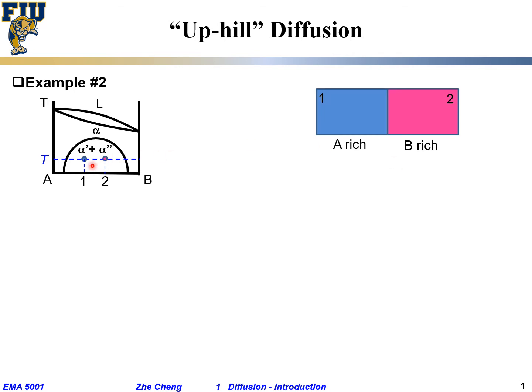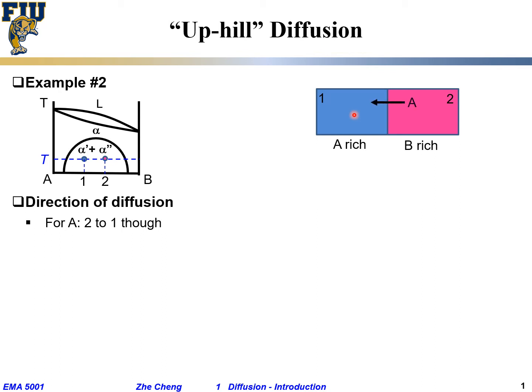When we put them together, based on the equilibrium phase diagram, will this eventually form a single-phase solid solution? No — we are in the two-phase region. In reality, people actually observe so-called uphill diffusion: elements will diffuse to the region that is higher in their own concentration, going uphill from a concentration point of view. For the A element, diffusion goes from piece two to piece one — from the piece that is deficient in A toward the piece that is richer in A.